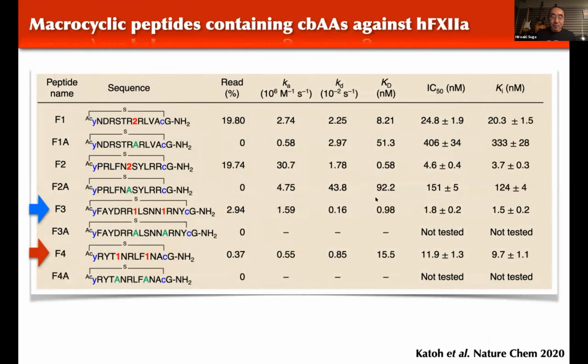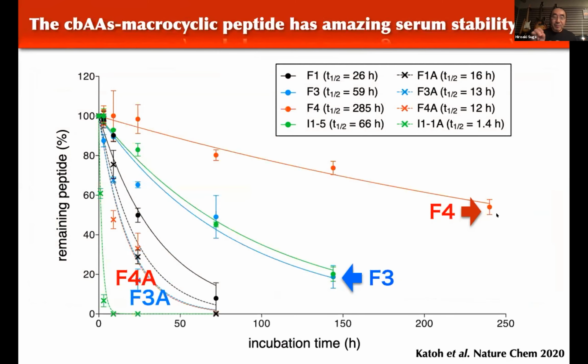This one is in the 1 nanomolar to picomolar range, and this one is also in the low nanomolar range. And these also strongly inhibit the target protein's enzymatic activity. And we looked at how stable this peptide is. Generally, peptides are very rapidly degraded in serum. On the other hand, the peptide we generated with this method is intact over 10 days. So a really stable peptide can be generated.